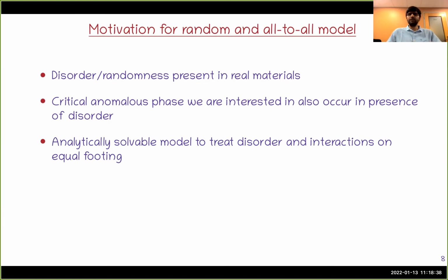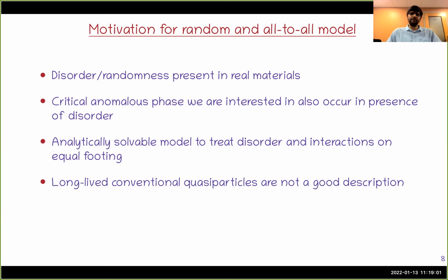And at least from the theoretical point of view, we want an analytically solvable model where we can treat disorder and interactions on an equal footing, which is kind of hard. In this model, as I will show you, it seems to be very naturally the case that we can treat these two things on an equal footing and in a very systematic fashion. So that's why this is an advantage. And one interesting thing is that any theory based on long-lived conventional quasi-particles, like in terms of Cooper pairs, or if you start from a Fermi liquid theory, then you simply cannot get this anomalous phase. People have tried this in the past, and if you start with conventional theories with conventional quasi-particles, it's simply not a good enough description for these anomalous metals.